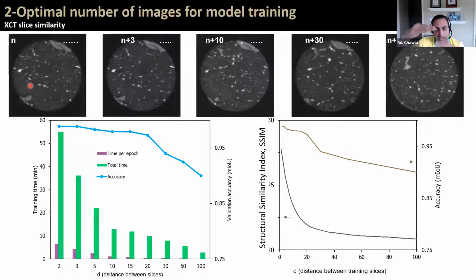And so we started looking at how far away from the initial image we need to get the next image, so n plus 10 or n plus 30. And as you would expect, there is a sweet spot here. When we get to a distance between slices of somewhere between 5 to 15, we get no real reduction in the accuracy, but we also get a reduction in the training time. That's what we're looking for. So that's really the point here: we need to have unique images if we want efficient training of the machine learning algorithm.